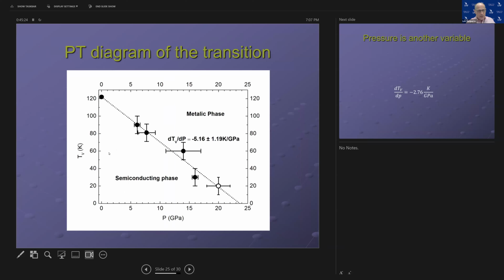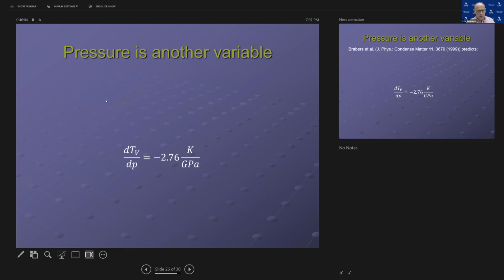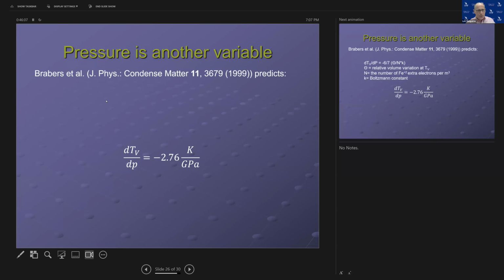So this is the result of the several experiments, and it's pretty much this line that separates the metallic phase from the semiconducting phase. So there are two phases here. As you can see, the pressure went from 0 to 25 gigapascals and temperature from 0 to 120 K. So at ambient pressure, the transition is at 120 K. As you increase pressure, the transition drops. From this graph, you can figure out the slope of the line, and then you can compare it to the prediction of Brabers.